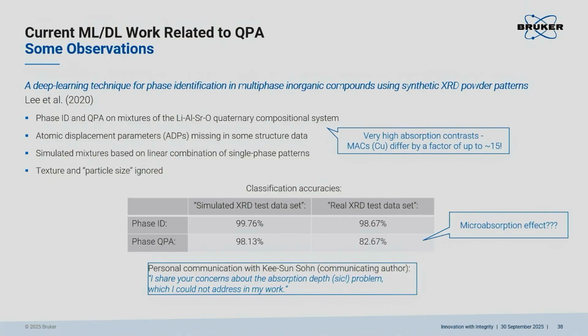But what happens then is they observe perfect phase ID results for their phases here with very high classification numbers, 99%, 98%, but a large discrepancy to quant results, and they wouldn't know why. But if you have a look at the samples they were using, they did QPA on mixtures in the lithium, aluminum, strontium oxide system, which should ring an alarm bell instantly. So I contacted the authors, and they said, and this is a citation, I share your concerns about the absorption depth problem, which I could not address in my work. So I'm not saying that these authors did not know about microabsorption effects. I cannot claim that, but I can claim they entirely did not consider it.